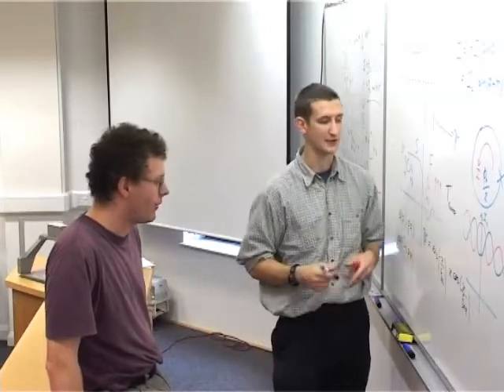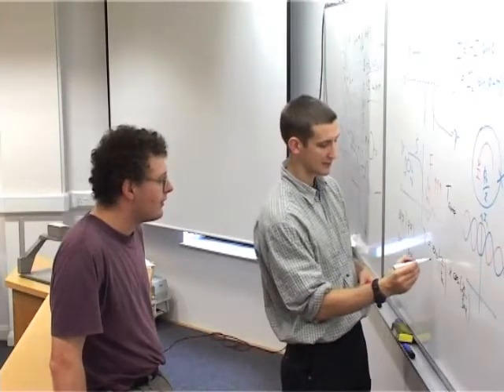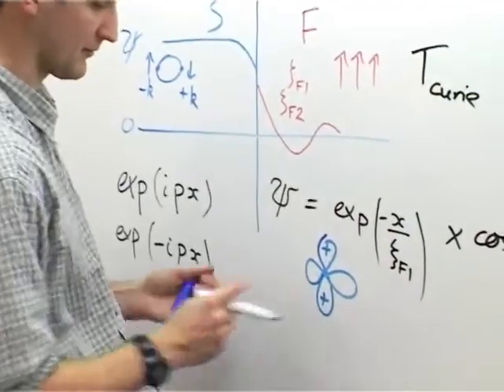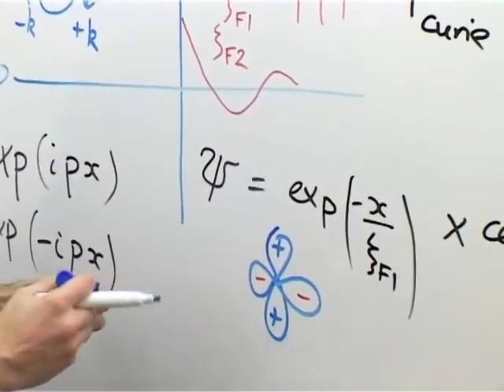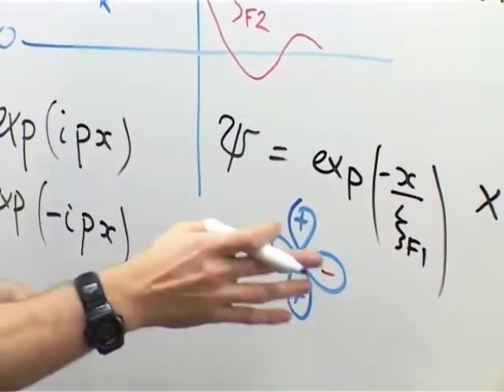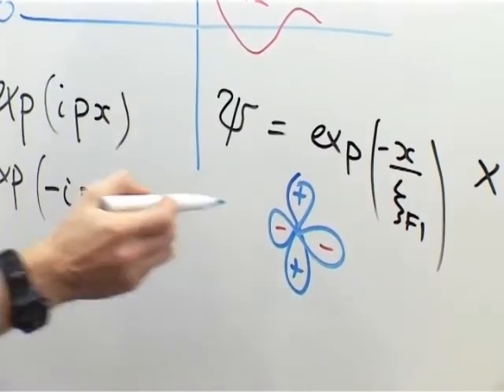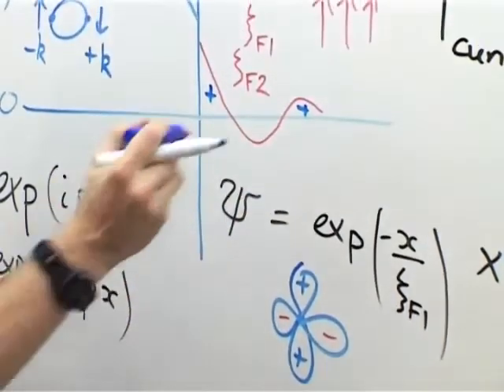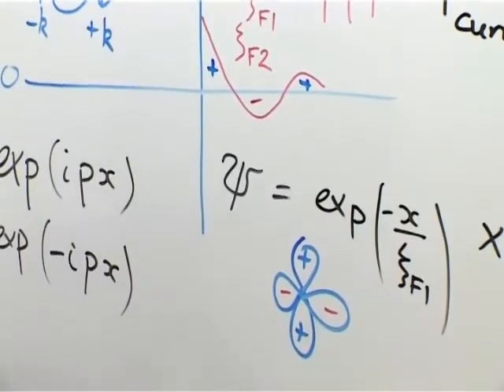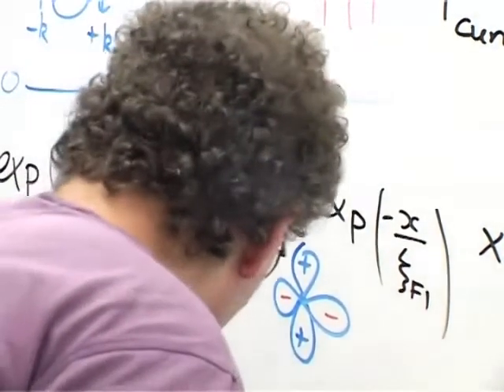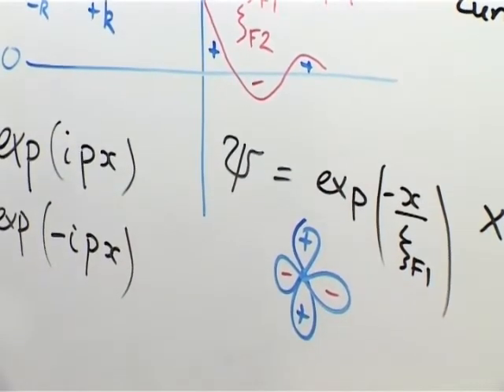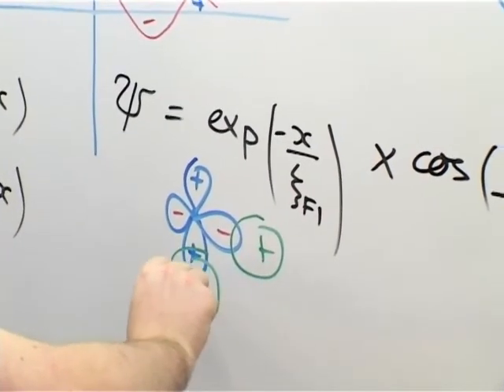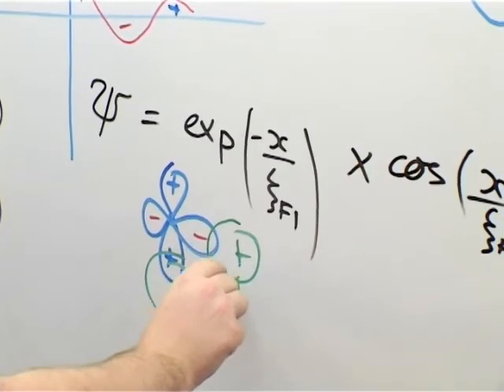So that's the sign change. The sign change, in the D-wave case, when you have your D lobes, you have positive and negative signs to your order parameter in something like the high T_C superconductors. These positive and negatives are very closely analogous to the positives and negatives we have in this system. So you can actually achieve exactly the same type of effect with the high T_C compared to the ferromagnets.